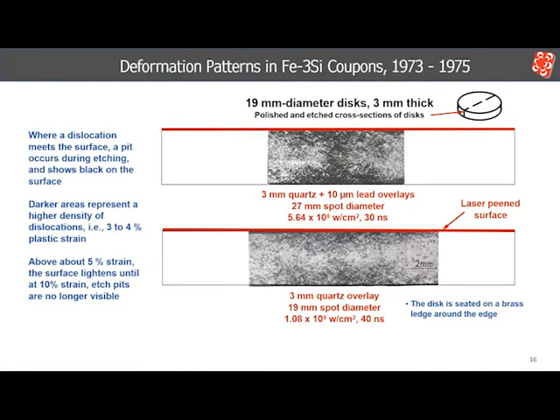Here we are going to look at the deformation patterns produced by laser shocking iron silicon discs. The plastic strain distribution can be seen by applying an etch pitting technique to the surface of the laser shocked cross sections of the alloy. Plastic strain occurs by the motion and multiplication of dislocations in the metal lattice. After sectioning the disc and preparing the cut surface, each dislocation appears as a dark spot on the surface. Up to about 4% strain, individual pits are distinguishable. Between 4% and 7% strain, the areas get darker, and above 10% strain, the surface again appears light.